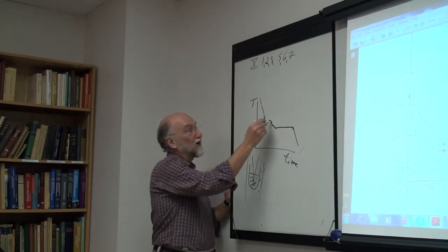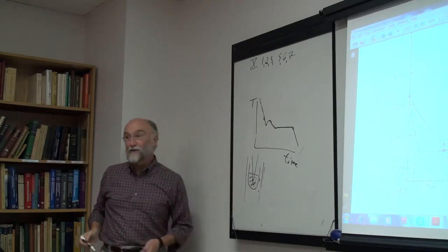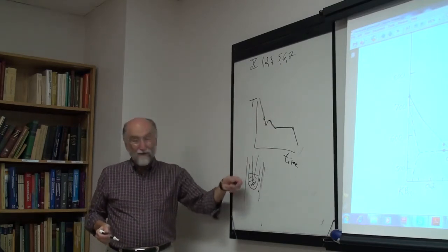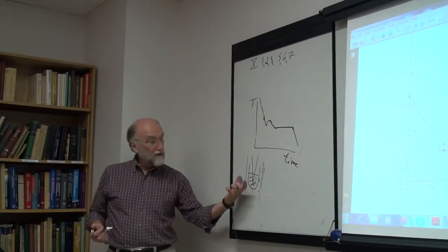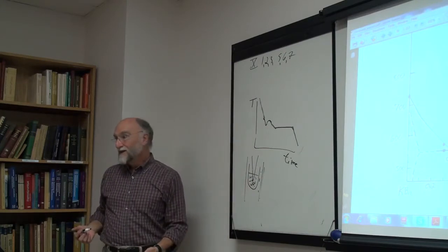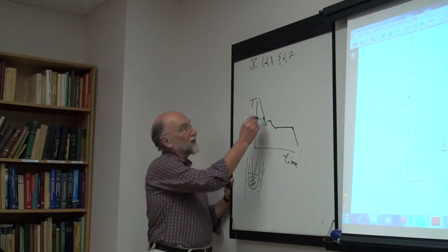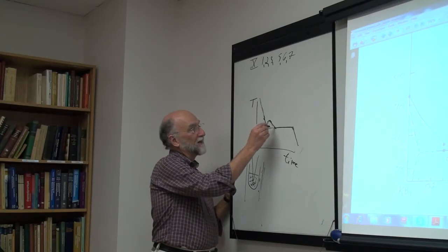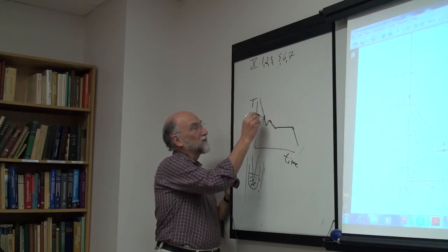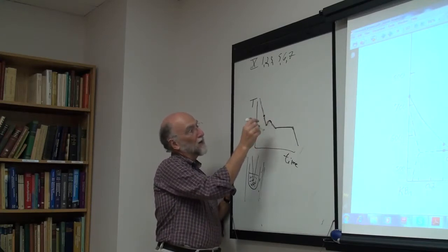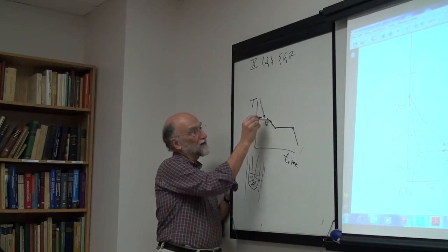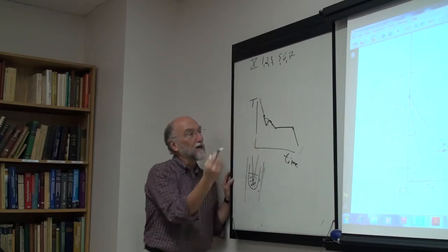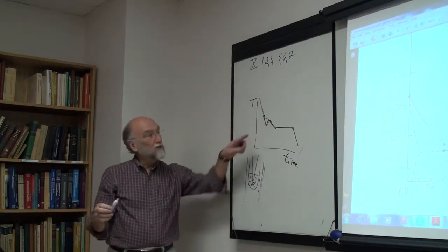Now if you do, this is called thermal analysis, not differential thermal analysis. This is good old-fashioned thermal analysis with a great big sample, and you're cooling it. So you're going to get a curve that looks like that. Now, if you haven't got too much supercooling, it's usually fairly obvious how this can be extrapolated back up. It's not a straight line, but usually it's not too bad.